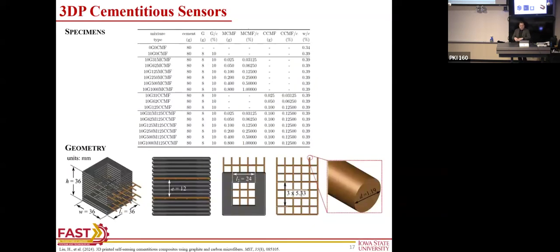Here, we'll try different mixes. That's all you do when you look at the percolation. So you try different amounts of graphite, different amounts of microfibers, and try to plot this S curve to know where you can be in that percolation threshold.